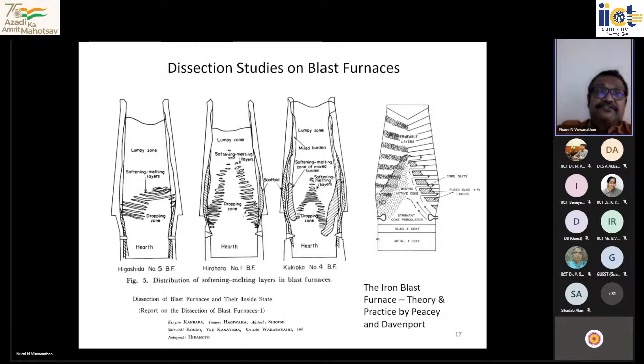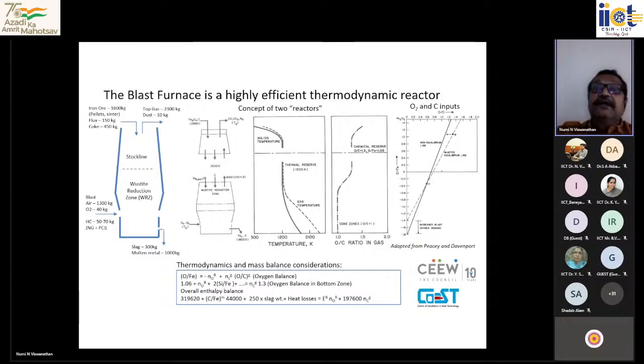Of course there are also measurements which were done. Just to tell you, these measurements were done during our project at NML, with Tata Steel, Bokaro, all those places. Again, making these measurements is not easy because this will be approximately 30 meters or so. So you have to put a probe at the top, and that has to descend with the whole charge. These are all huge systems. And then till it becomes molten, you hope that it will give data, and that way they try to measure the temperature, composition, etc. Such things have been done elsewhere also. This is one such, for example, composition measurement. And one of the things which they found out through all these measurements was there is a zone where the composition as well as temperature remains constant in the furnace.